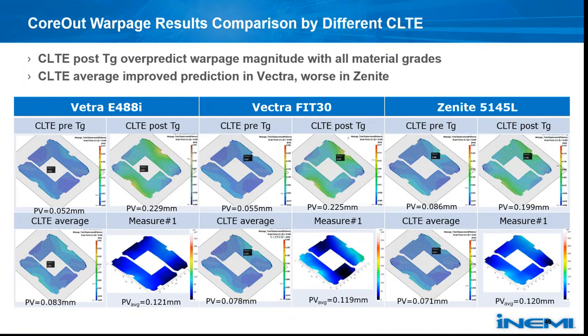Okay, so similar results are shown with the core design. The warpage predicted by the CLTE pre-Tg is much lower than measured, and the CLTE post-Tg predicted almost twice the measured data. And the CLTE average is the closest as compared to the experiment.